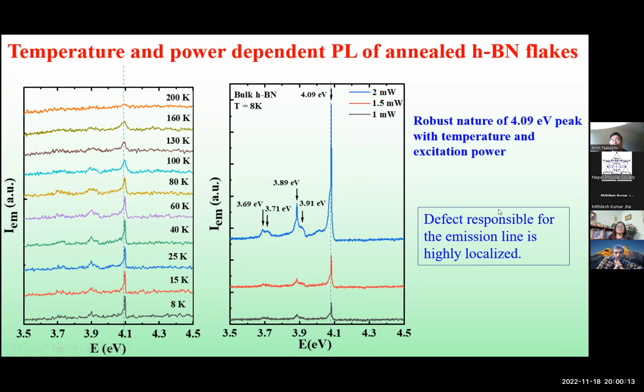So what does that mean? The energy peak position is robust, meaning it is not affected by temperature and not affected by higher excitation. The material is not affecting its property, but is simply behaving as a host. Normally this is because of a point defect. So there is a point defect inside the material, hosted by boron nitride, and what we are seeing is from that defect. Those defects we call highly localized, and the material is simply the host.